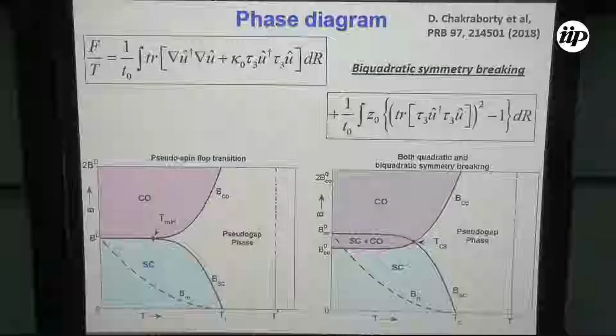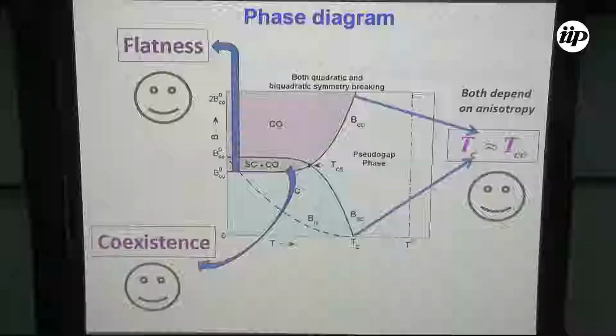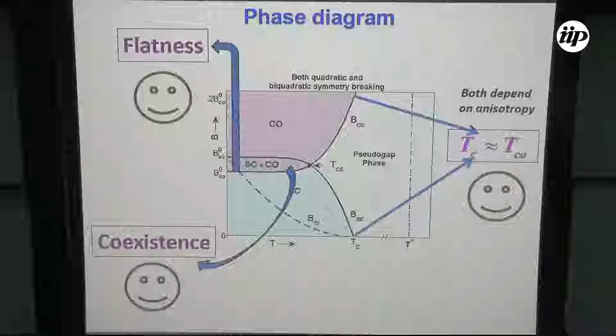This is just mass being different. Now you have to make higher order corrections. And by this symmetry breaking, we can get the coexistence phase here. So we are very happy because we got the flatness that was there in experiments. We got the coexistence phase. And because of this symmetry between the two energy scales, what we also see is that the zero field transition temperature for superconductivity, Tc, is very close to the high field transition temperature for the charge order.